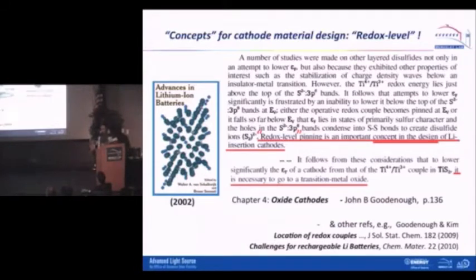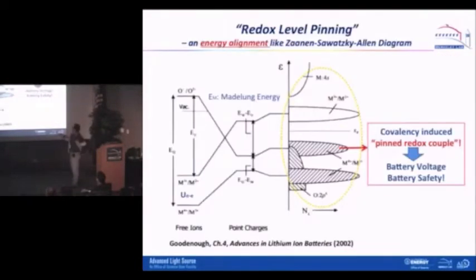So what is this redox coupling? This redox level pinning is a little fundamental physics, but it's fairly easy to understand. If you look at the free ion energy level, your oxygen -1 or -2 is always sitting above your vacuum level. That's why it tends to become oxygen 2-. It's the so-called negative electron affinity. And your transition metal with different valency will sit below the vacuum level. When you bring them into an ionic system, all those energy levels will be adjusted by the ionic energy. We call it Madelung energy.